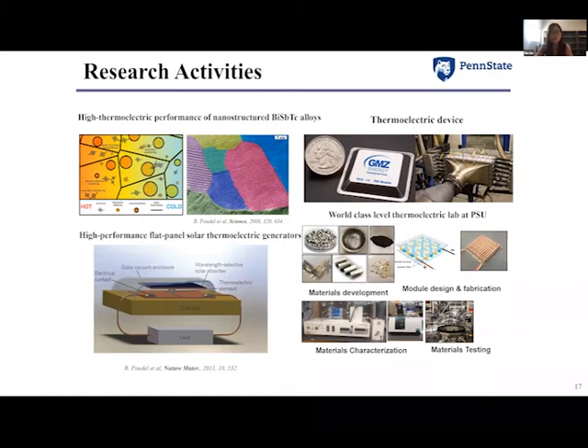And can achieve a peak ZT of 1.4, which is a 40% improvement compared to the state-of-the-art result at that time. So this breakthrough was published in Science and promoted the real application of bismuth telluride-based thermoelectric materials in waste heat recovery, air conditioning, and also refrigeration applications.